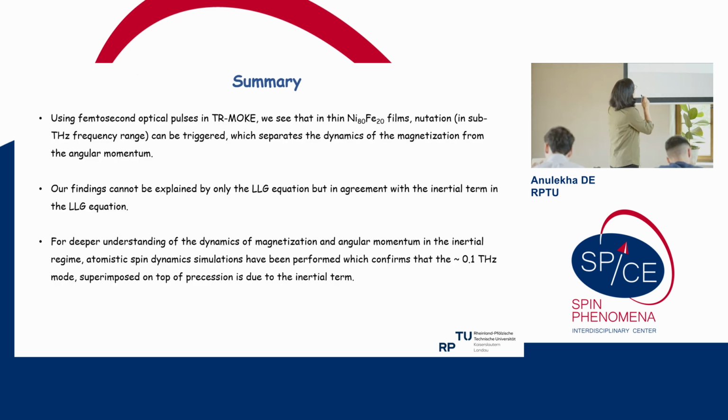So to summarize, using an all-optical femtosecond laser pulse in time resolved mode, we can excite nutation superimposed on the precessional dynamics. This high frequency nutation oscillation cannot be explained by the conventional Landau-Lifshitz-Gilbert equation, but we have to consider the additional inertial term in the Landau-Lifshitz-Gilbert equation. And this nutation frequency is almost invariant with excitation fluence or the applied magnetic field.